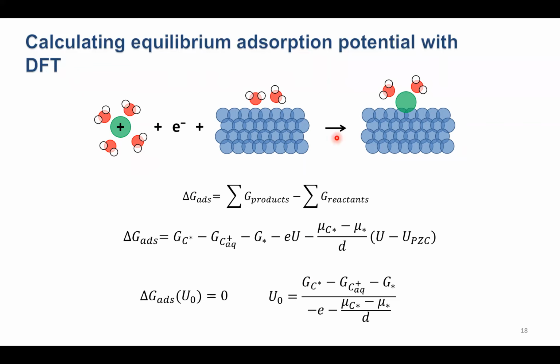But basically, we have some generic adsorption reaction shown on the top of the slide here. We can use DFT to find the free energy of each of our reactant and product states, and use that to calculate the free energy change for adsorption. That's just the free energy of the products minus the free energy of reactants. And that delta G will tell us when that reaction becomes favorable, at what concentration of species in solution and at what electrode potential. Typically, what I'll show in the talk is actually not delta G as a function of potential. Instead, I'll solve for the potential that gives us a delta G equal to 0 and call that our equilibrium adsorption potential.